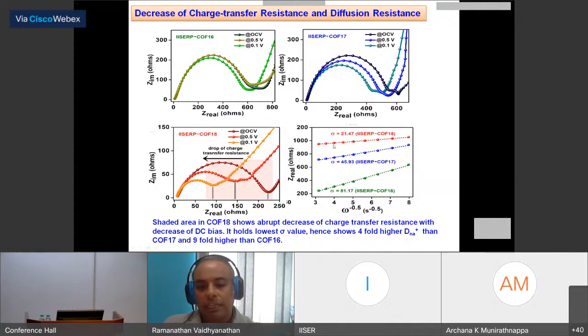And here is the impedance spectroscopy, which shows why the COF is performing very well, because the charge transfer resistance drastically decreases as I take it from the all-carbon form to the pyridyl plus tetrazine form. And this decrease in charge transfer resistance is exactly what gives rise to an excellent diffusion of sodium ions into the anode developed with this COF. And you can see the sigma value is the lowest for the tetrazine pyridyl containing COF.